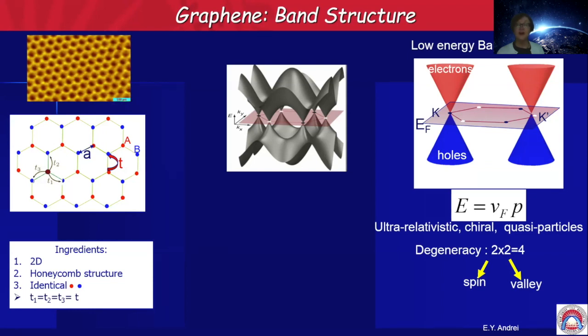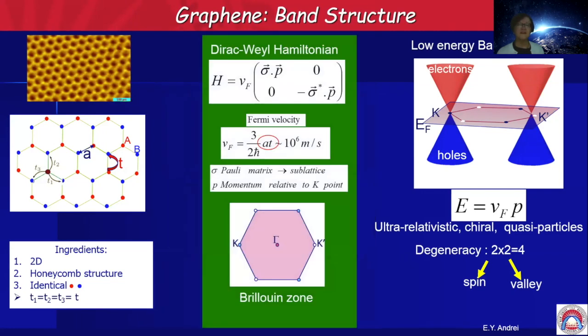These two cones, which are not identical, are related by time reversal symmetry. The Fermi energy sits right here, and this is our hexagonal Brillouin zone. These two cones we call K and K prime. So we call them valleys. This is more for the experts. The dynamics of the electrons in this system is determined by this fairly simple Dirac-Weyl Hamiltonian, where sigma here is a Pauli matrix that operates now not on spin, but on the sublattice degree of freedom, A or B, and p is the momentum relative to these K points. Now, the velocity of these ultra-relativistic electrons is about 1/300th of the speed of light.